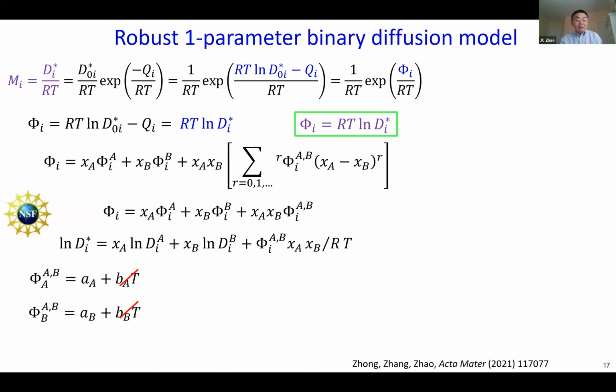So we went ahead and tested all those different combinations. We tested the 4 parameters. We took out the temperature dependent one, leaving 2 parameters, and then we set those 2 equal, so 1 parameter. What we found is that you can simplify the binary diffusion and still have an extremely good description of the system behavior by taking out all the temperature dependent terms. You never need that. We tested it in 18 systems.